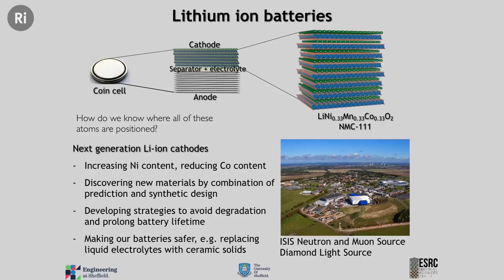So what can we do to try and mitigate these degradation processes? Well, when we look towards the next generation of lithium-ion battery materials, and when we look at cathodes in particular, where are we moving to? We can increase the nickel content of these battery materials to try and up that capacity, try and reduce the cobalt, maybe even completely eliminate it. We can try to discover even new materials, and we can do that by combining things like computational insights from calculations with some synthetic design procedures and try and come up with a new family of materials. We can design strategies and develop strategies that avoid degradation and prolong battery life.